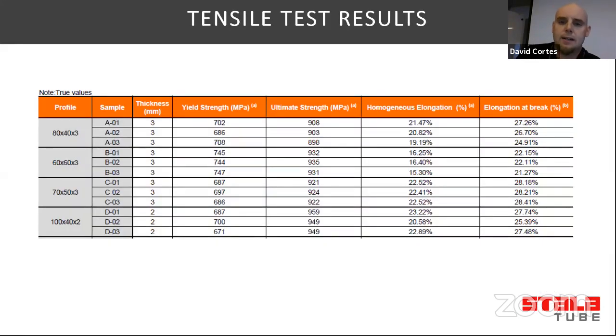Here we have some actual tensile test results for those hollow sections. You can see the profile size on the left-hand side. So typically, as you can see, the yield strength is around 700 megapascals. The ultimate tensile strength is more than 900. And still the homogeneous elongation is about 20%. And the elongation at break is always above 20%. It's typically about 25%. So this basically means that these can handle a lot of bending, buckling, all kind of damage before they break.